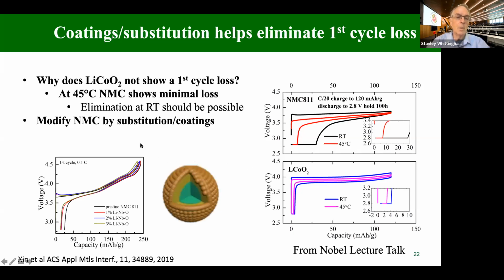So what we did, we decided to modify these layered oxides by either substituting elements inside it or by coating it. In our initial studies, we used a lithium niobium oxide solution, which we soaked the meatballs in, and then we fired the materials up to about 400 degrees centigrade. What you now get is a niobium containing layer on the outside, and this goes into the bulk of the material just a few nanometers. The center is left the same.